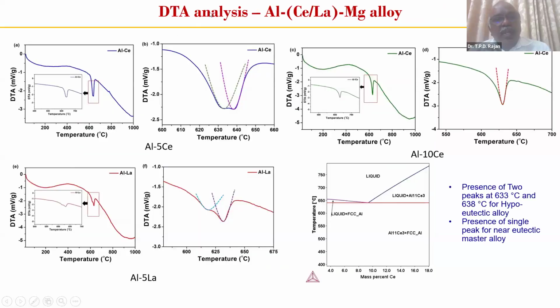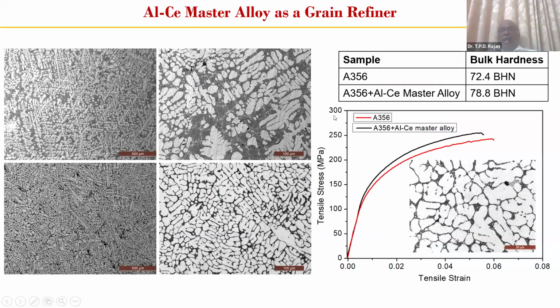And the DTA studies have also shown the formation of these aluminum-cerium phases. Especially, we can see that at a higher percentage of cerium, it forms the Al11Ce3 phase, which is a eutectic phase normally used as a grain refiner in aluminum alloys. These are all about the enhancement in the properties of cast alloys by the addition of a minor amount of cerium, which increases the hardness as well as the mechanical properties by the reduction in the grain size.